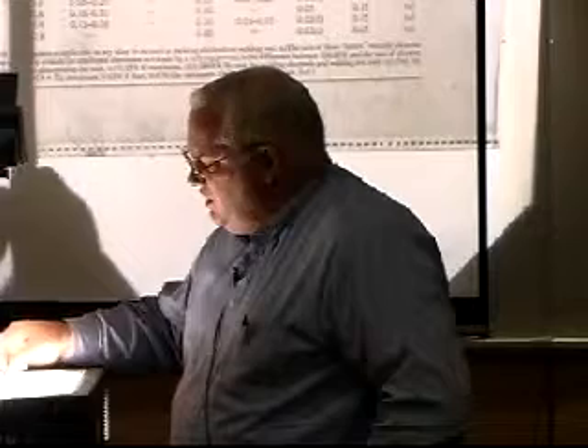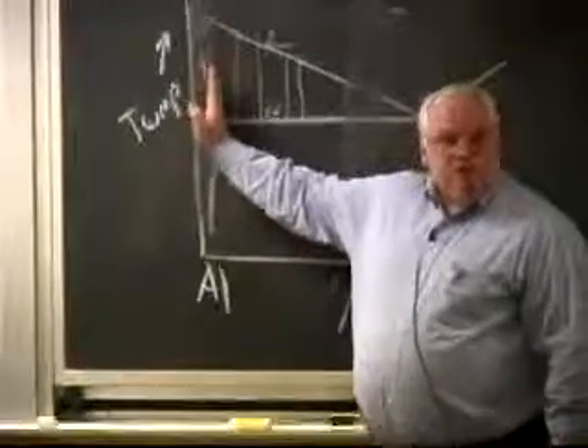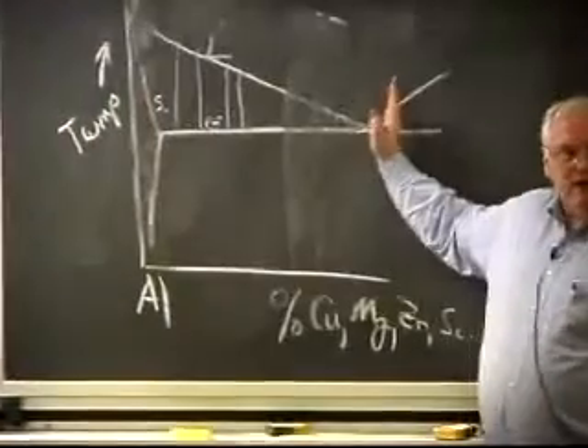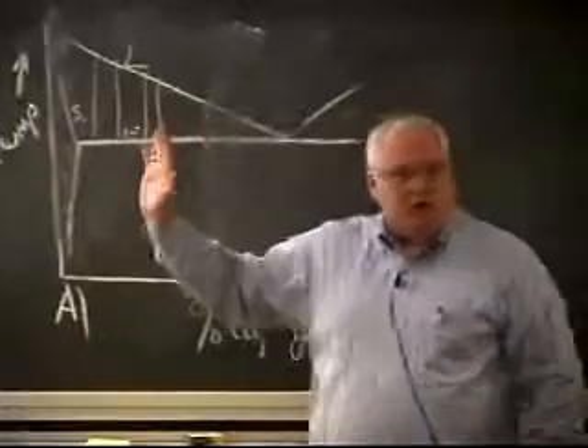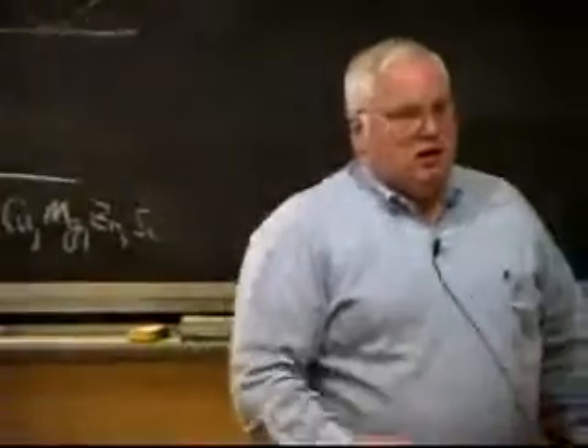If you look at magnesium, you find a bunch of alloys that are no more than 1% magnesium, and then you see there's one here that goes between 1.1 and 1.8, but then you see everything jump up to 2 or 3 all the way up to about 5% magnesium. And what you've done is, by looking at either copper or magnesium, you're either very lightly alloyed or you're very heavily alloyed. And you avoid this region in between because of the tendency to hot crack because of wide freezing ranges. Wide freezing ranges are bad in welding in general, not just in aluminum alloys, because of this tendency to build up strain in the liquid solid mushy region.